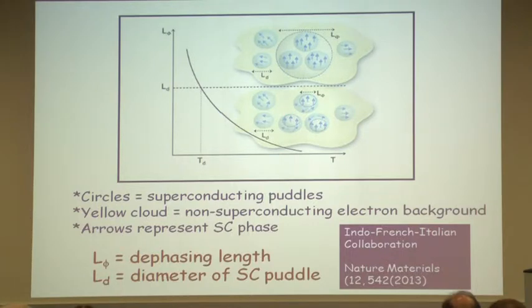Now there are two length scales in the problem. One is the size of the puddle, L sub D, and the second length scale is L sub phi, that is the phase correlation length, the length scale over which one puddle talks to the other puddle. So there is a phase correlation. Now if I look at the evolution of this phase correlation length L sub phi as a function of temperature, this is how it goes. Above this temperature T sub D, my L sub phi is smaller than L sub D. So I'm in one regime where the puddles are not talking to each other. That is my first quantum phase transition. And once I go to very, very low temperatures, my L sub phi becomes larger than L sub D. Now the puddles talk to each other, and we are dealing with a different state. And this manifests itself as a separate value of critical field BC and the critical resistance RC.